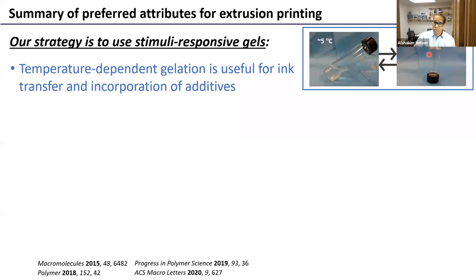At room temperature, we have this nice self-supporting gel. This is a magnet that's suspended in that gel there. But if you stick this gel in a refrigerator or an ice bath, then the gel will melt. And this is a reversible process. And when it melts, it very readily flows. Okay? It's liquid.